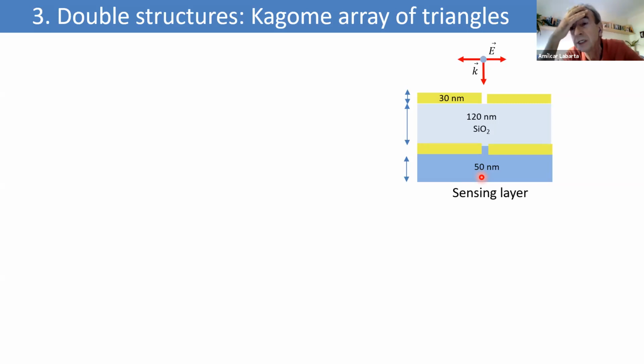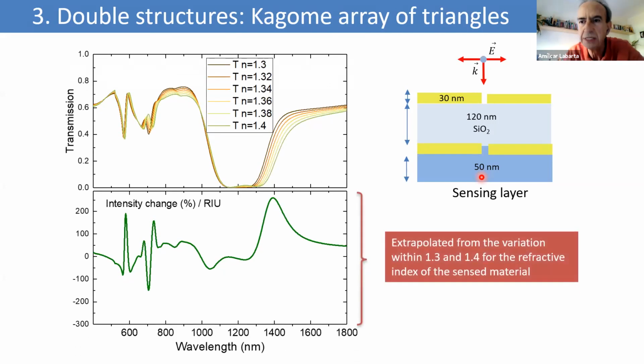You can put this water in contact with one of the structures, and then try to detect the change in the optical properties of the structure due to the change in the refractive index of the sensing layer, due to the presence of these extra species that you want to detect. Of course, this is a proof of concept, but let me show you the transmission of this double structure of Kagome lattices. And here you have results corresponding to different values of the refractive index of the sensing layer around the value of the refractive index corresponding to water.